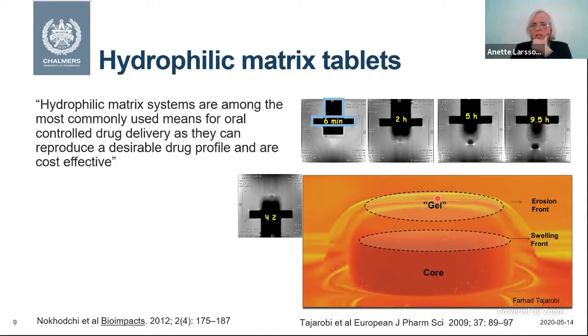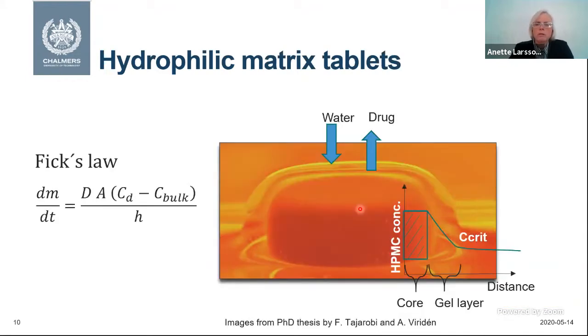And here, what we call a gel is not really a gel. It's a polymer solution with a very high concentration, and they have a concentration gradient here. In between, what is called the gel in pharmaceutics, and the bulk surrounding it is called the erosion front. If we take a look here, the water goes in, and the reason why water goes in is that, since it's a hydrophilic polymer, the system will gain energy if it dilutes, conformational entropy in that case. And when the water goes in, the drug will dissolve in the gel layer and can diffuse out. This creates a core with constant concentration of HPMC, and then it decreases.